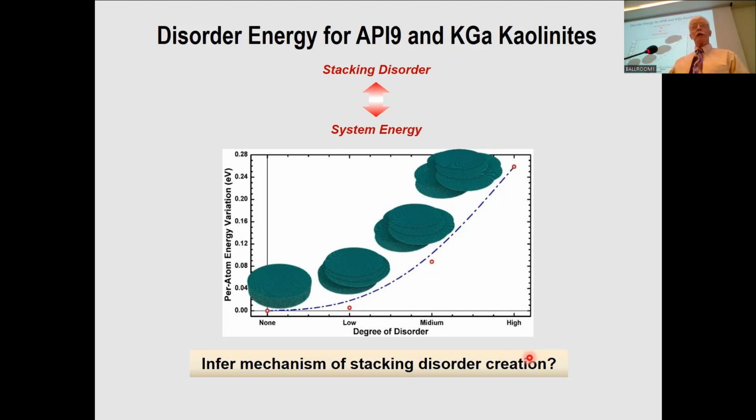of these disorders? If any of you is lucky enough to have ever worked with Kaolinite and you happen to put it in your mortar and pestle and grind it, you will find that you destroy it. Well, you affect the layer stacking order tremendously. And so it's very easy to cause changes in the layer stacking order. You can imagine if you extract something from a soil that formed in situ, it would never have had any mechanical effects of the sort that you might find in a river sediment.